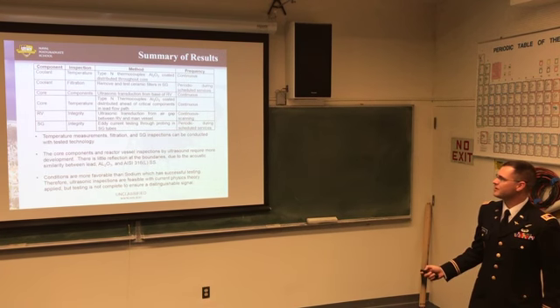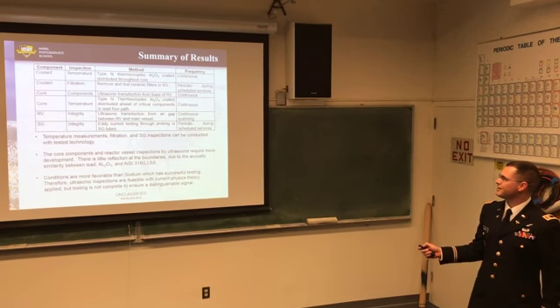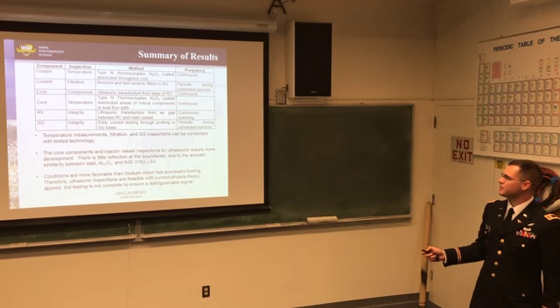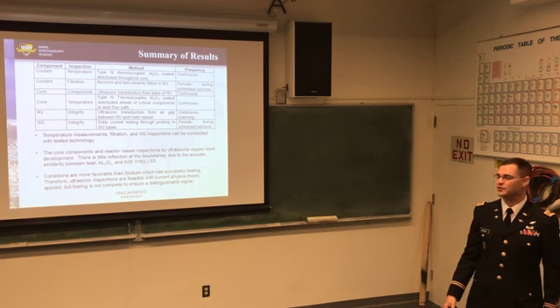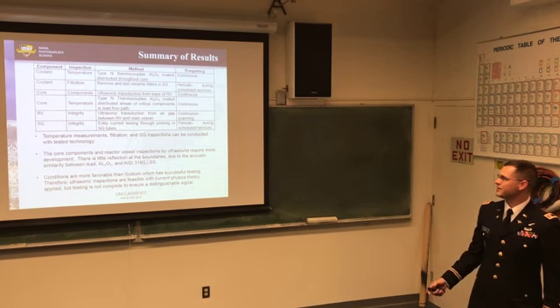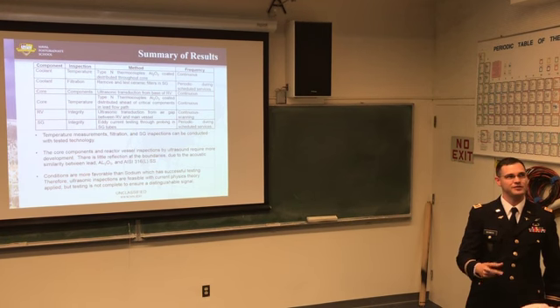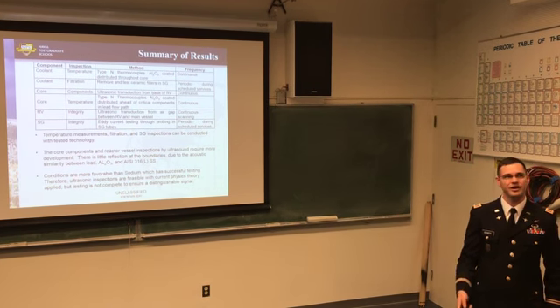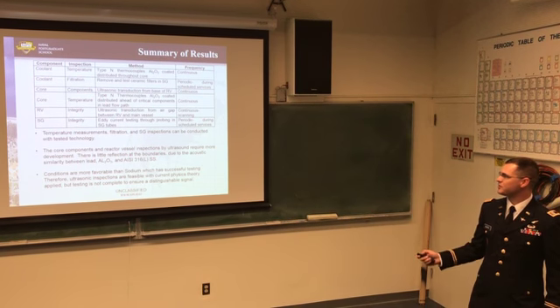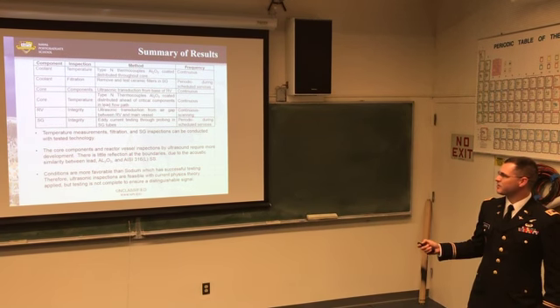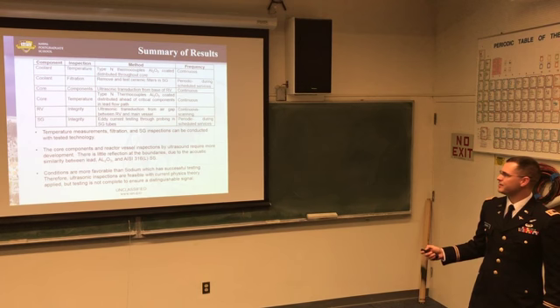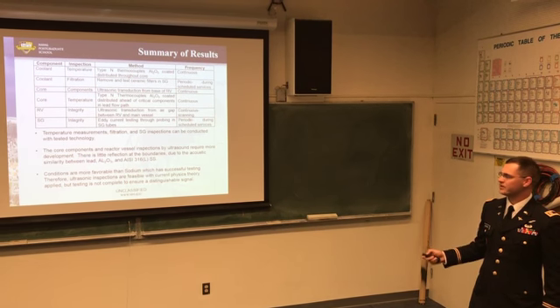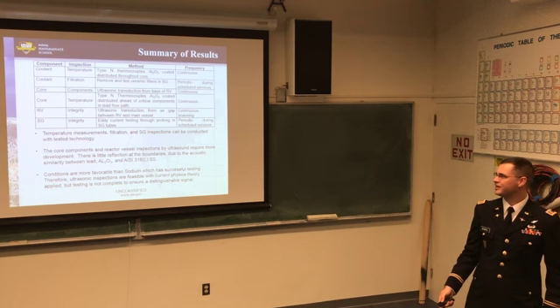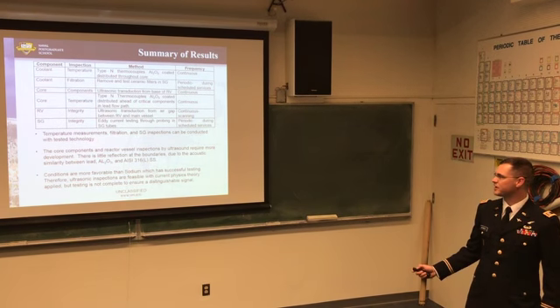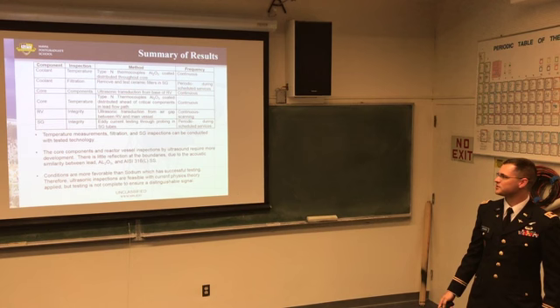So summarizing our results, the coolant temperature and filtration: these can be done through temperature with our N-type thermocouples over a continuous period. Filtration was identified as something that's not really unique, but it has to be done during periodic outages in the steam generators. Core components: ultrasound, and the core temperature with our thermocouples again. The reactor vessel integrity: eddy current testing wasn't quite successful, so ultrasound. And for the steam generator integrity, eddy current testing would be more than sufficient.